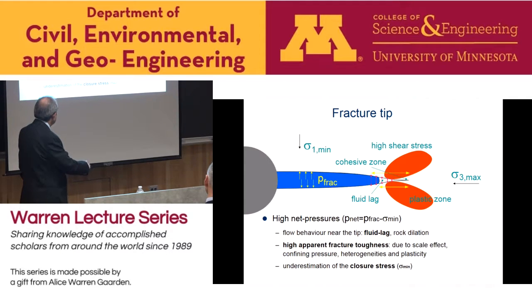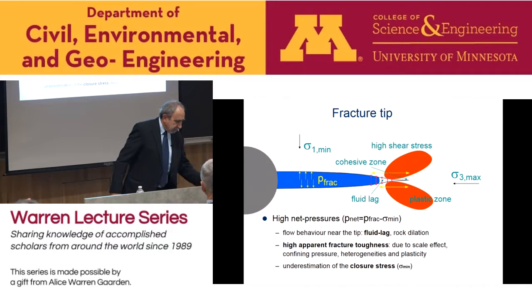In the work here, I tried to look at these different approaches, and I set up a fully coupled hydraulic fracturing model, focusing in my work on weak rocks. If we try to do hydraulic fracturing in a weak rock, due to high shear stress concentration around the fracture tip, the rock will yield. And these plastic zones are very important because the energy is dissipated in these zones, and we need much higher pressure to propagate the fracture. We can see later what that means in terms of the effective, or apparent, fracture toughness.